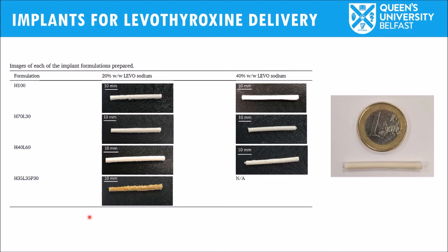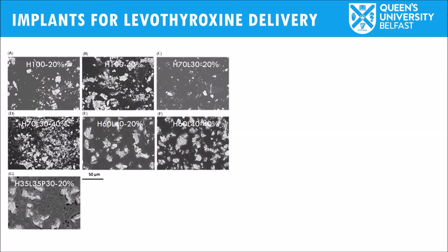And actually that was the case. We didn't even bother preparing one with higher levothyroxine content, because we could see that polyethylene glycol was degrading the drug inside the implant. We established that levothyroxine is probably quite susceptible to humidity, and polyethylene glycol is going to make the implant attract water content and ambient humidity, and that's what is going to lead to the degradation of the drug. Whenever we observe the implants under the microscope, you can see the crystals of the drug, because levothyroxine is not soluble in DCM. The polymer was dissolved but not the drug, so it was a dispersion, and we used a speed mixer to mix these formulations.